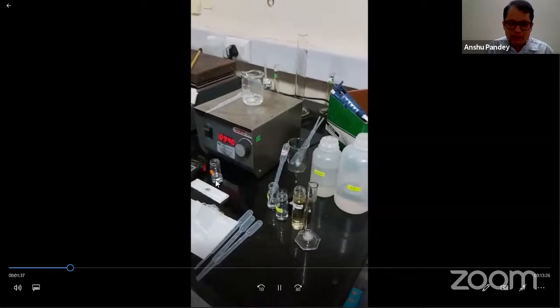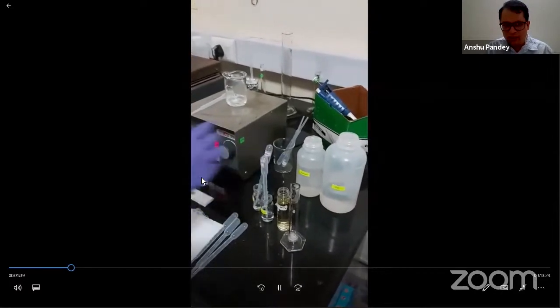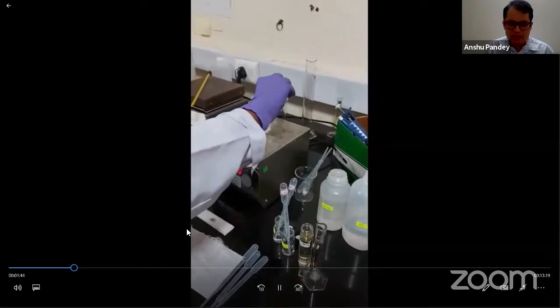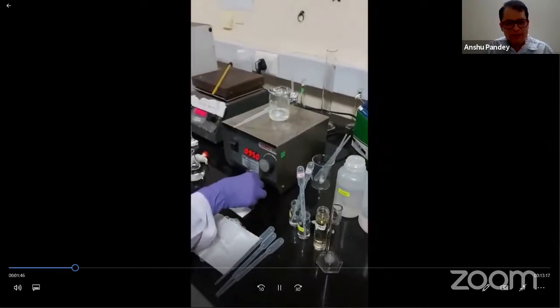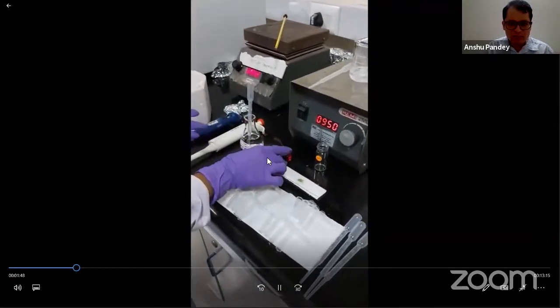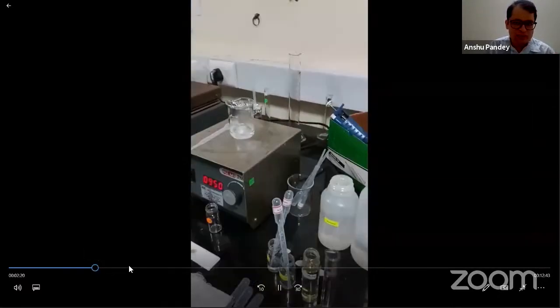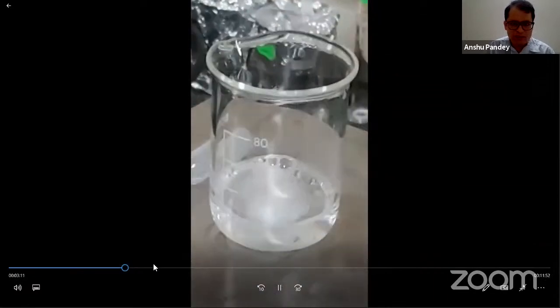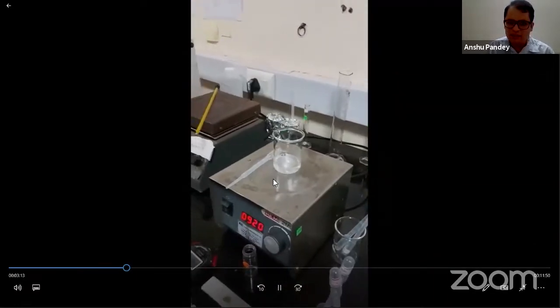Lastly, she has a measured amount of silver nitrate in a vial right in front of her over there, which she now adds. So as soon as she does that, she also starts a clock. This is around the 90-second clock. So that is where we start measuring the time. This is roughly the optimal time which it takes to prepare these initial silver halide clusters. So I can wait or I can skip over the 90 seconds. So you can see that there's nothing much happening. There's a little bit of turbidity which does emerge.